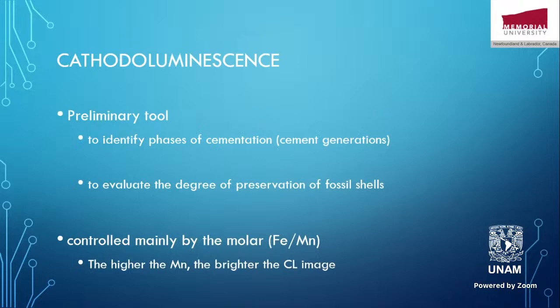That energy gained during the excitation is called quanta or quantum. When the electrons come back to the ground energy level, they lose that quanta in the form of luminescence. That's basically the concept of luminescence. There are elements in the calcite that enhance the luminescence, and other elements that quench the luminescence. For example, iron quenches the luminescence, it makes the luminescence dull, but manganese enhances the luminescence, it makes the luminescence very bright. This is why the molar ratio of iron over manganese is the ratio that controls the luminescence in carbonate.